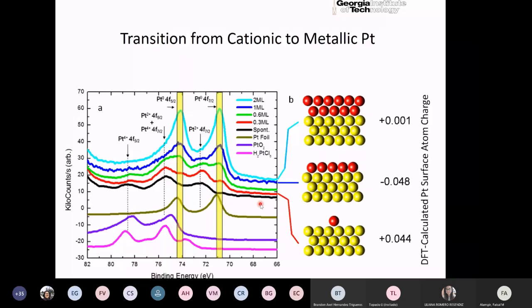All right, all this led us to then do some investigation on the computational side. We wanted to know how stable the 100 platinum is against platinum dissolution. And what we find is that, first of all, when you look at the band structure, you see that there's a lot of alignment of the electronic structure between the d electrons of platinum and the p electrons of carbon from the graphene. You can see that the peak positions are lining up, right?